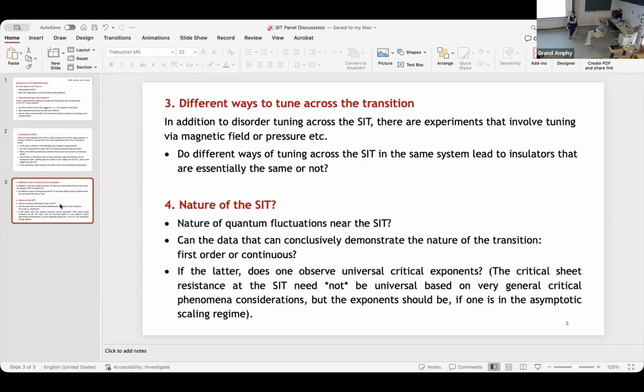But when we go to very thin films, about 3 nanometers or so, we see that these values differ by a factor of 2. So you get a much larger superfluid stiffness at gigahertz? No, for these samples we get a 4 times smaller value. So that would mean it would be even higher at the jump. Okay. That is true.